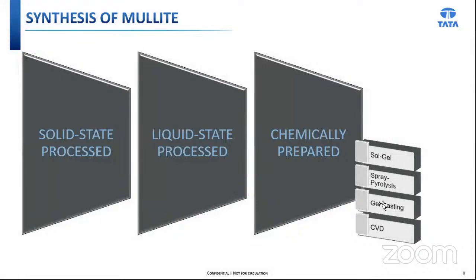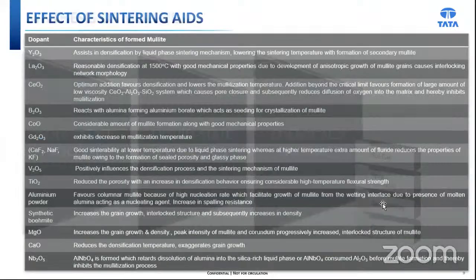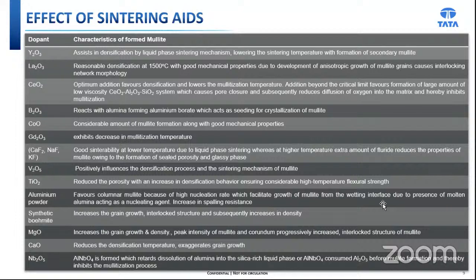Coming back to the synthesis of mullite, based on the different starting materials, a variety of mullite ceramic processing routes have been developed. This includes solid state derived mullite, liquid state derived mullite, sol-gel derived mullite, hydrothermally produced mullite, gas phase derived mullite, the spray pyrolysis approach, and processing with other miscellaneous methods. Mullite synthesized by liquid and solid state methods are designated as fused mullite and sintered mullite respectively, while the other methods are referred to as chemical mullite. Now these are the dopants that are used while preparing mullite, with brief characteristics of the sintered mullite produced, like yttria, lanthanum, cerium oxide, B2O3, cobalt oxide, gadolinium oxide, etc.